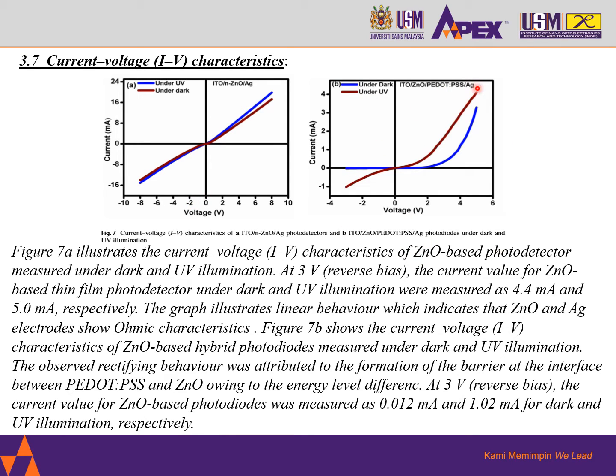Figure 7b shows the current-voltage characteristic of the zinc oxide based hybrid photodiodes measured under dark and ultraviolet illumination. The observed rectifying behavior was attributed to the formation of a barrier at the interface between PEDOT:PSS and zinc oxide owing to the energy level difference. At 3-volt reverse bias, the current value for the zinc oxide based photodiode was measured at 0.012 milliampere and 1.02 milliampere for dark and ultraviolet illumination respectively.